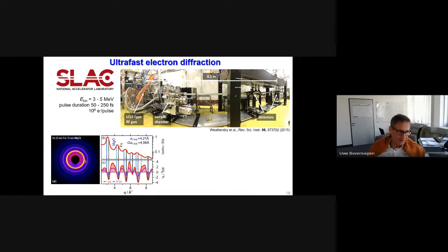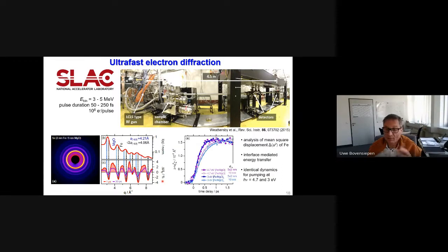So what Klaus analyzes then is the integration once around 2 pi, which shows then here this intensity as a function of momentum transfer Q. And the signal is strong enough that he can also identify changes upon laser pumping the system. Here you see the changes on the order of 1%. I will restrict myself to changes at iron. So iron and MgO have very similar lattice constants, and you can see tiny differences in the momentum transfer. But I will discuss here in my talk the changes at iron, which are here these black vertical lines. At longer delays, like 20 picoseconds here, for example, at larger momentum transfer, we can also identify peculiar changes in the MgO.